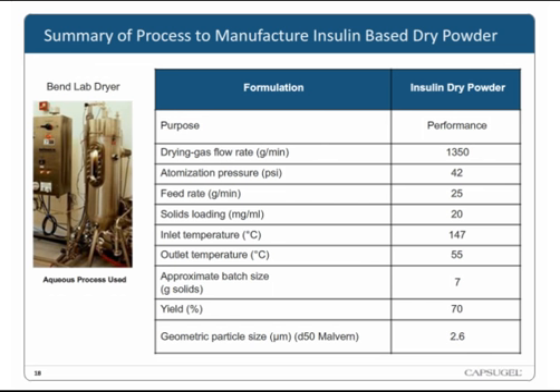But essentially, as Phil mentioned, for this specific study that's in the PharmSci Tech journal, we were looking at higher molecular weight polymers with hydrogen bonding sites to help stabilize the insulin and also give a really high-performing product because of the high glass transition temperature. It avoided adhesion between the particles. And we were able to do this very rapidly with a very small amount of API.